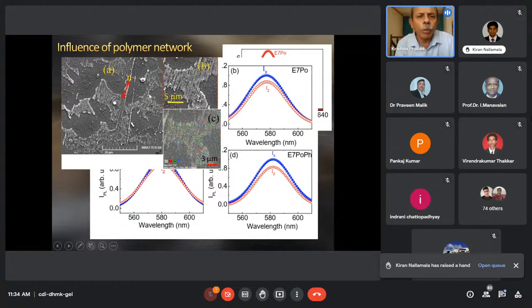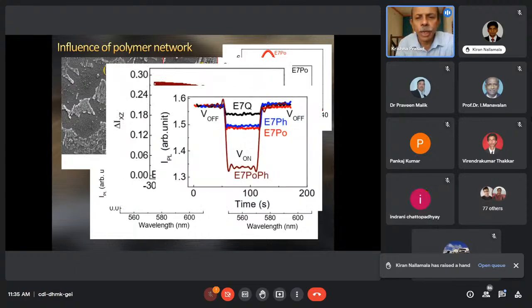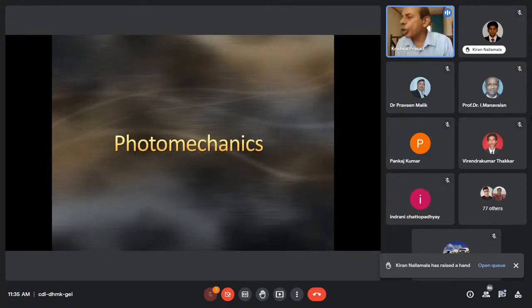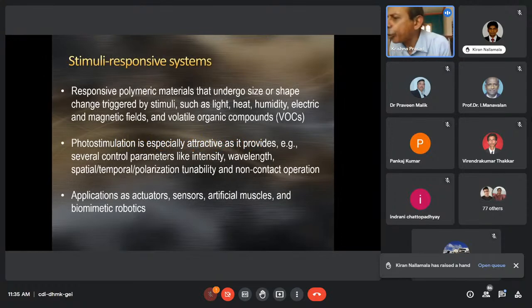You can see that the polymer network is the background, and the bright dots that you see, which is also confirmed by the EDAX kind of measurement, show that the quantum dots are very well oriented along the polymer direction, leading to high photoluminescence anisotropy in these systems. I'll skip that part and then go to the last topic that I want to mention, about photomechanics. I want to take some 3-4 minutes, and then I'll conclude the talk.